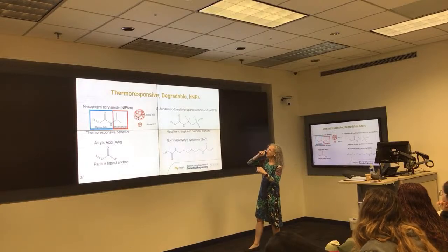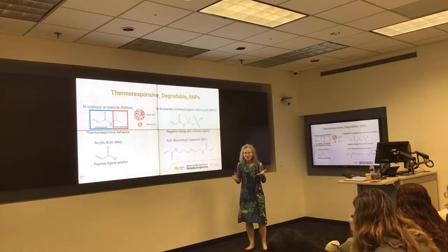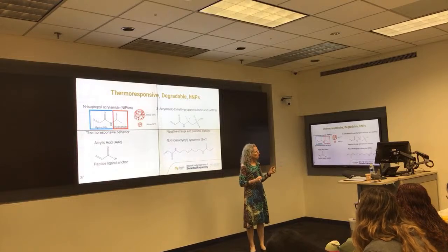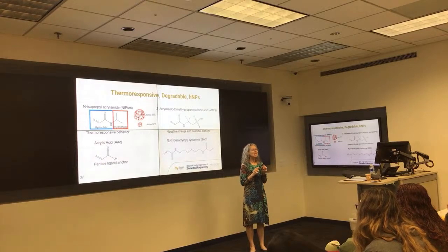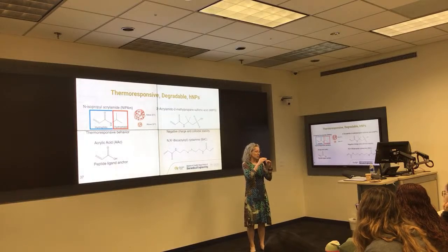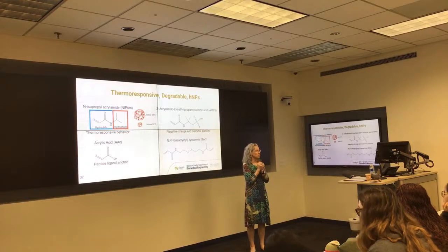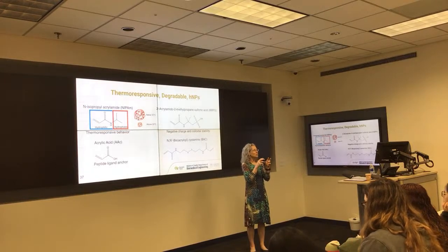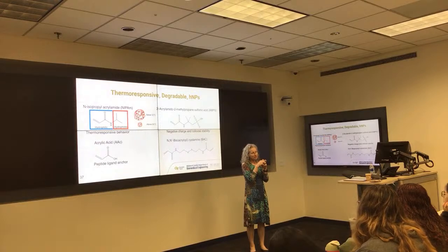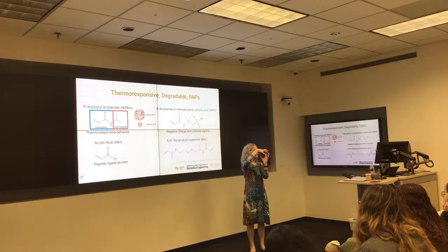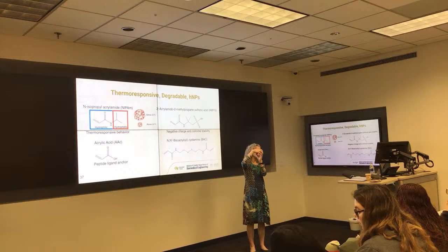But okay, so we're working with these poly(N-isopropylacrylamide)-type particles. And it's a really interesting polymer. So it's a little counterintuitive. It's thermoresponsive, and as you cool it down, it will go into solution, and as you heat it up, it comes out of solution, or it becomes like a polymer-rich phase. So it's the opposite of what you would expect, right? But what's interesting is you can cross-link it, and we form these little particles, and if we cool them down, they expand. They can't go into solution because they're cross-linked, right? But they'll expand, and then when we warm them up, they'll collapse.